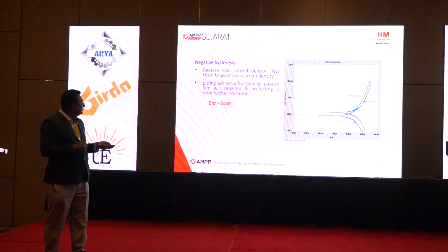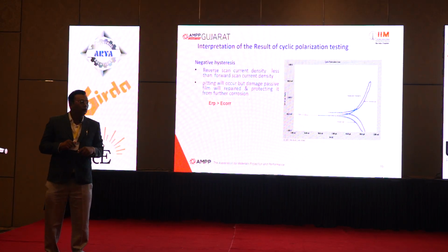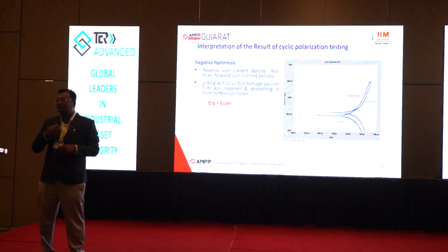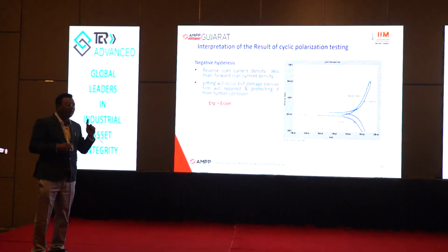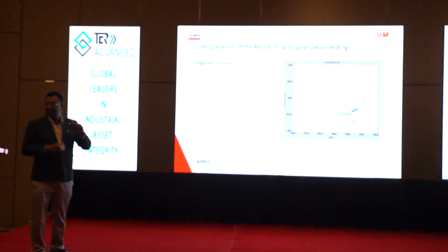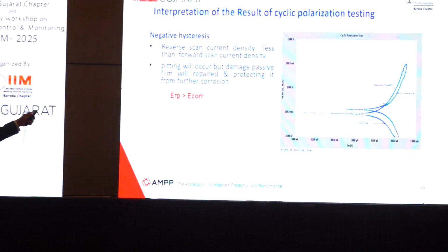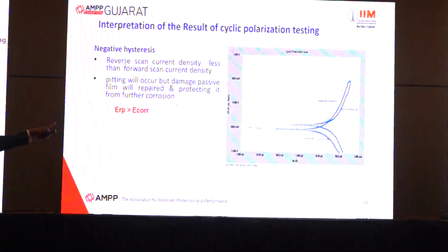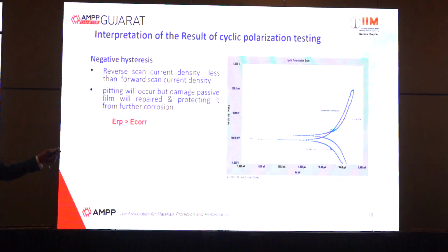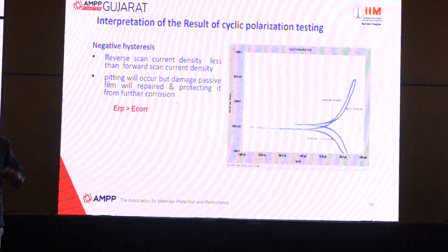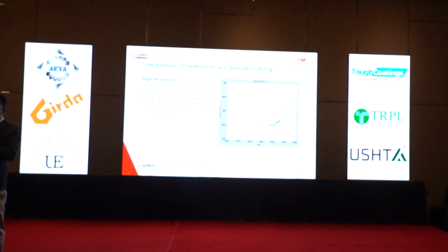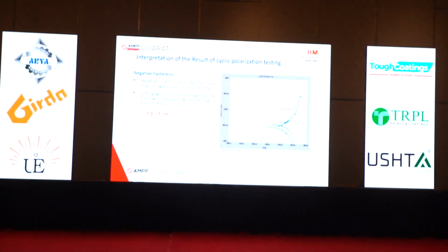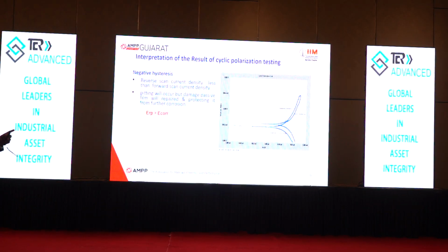The analysis is given by two kinds of loops, one called negative hysteresis and another called positive hysteresis. In negative hysteresis, the reverse scan current density is less than the forward current density, and the interception point, ERP, the repassivation potential, is greater than or equal to E-corr. In the potentiodynamic scan, this is the E-corr value, and wherever the reverse scan intercepts is the repassivation potential. When the ERP is on the passive domain side, at a higher value than E-corr, the damage will be repaired passively and it will prevent further corrosion.